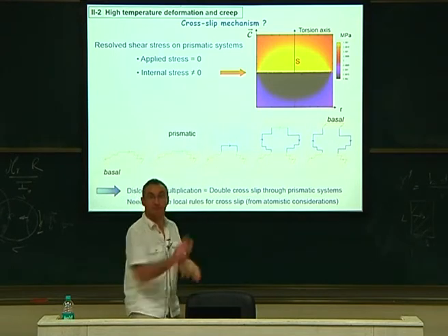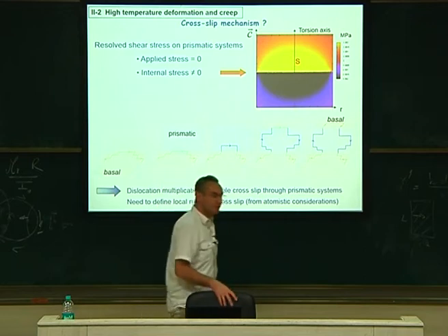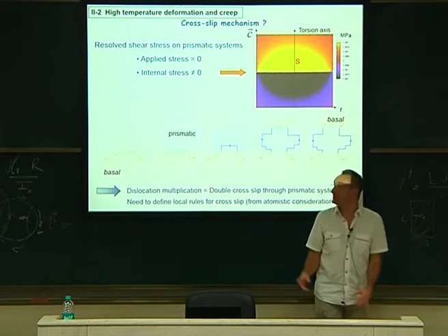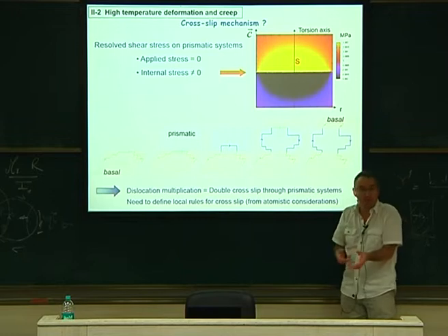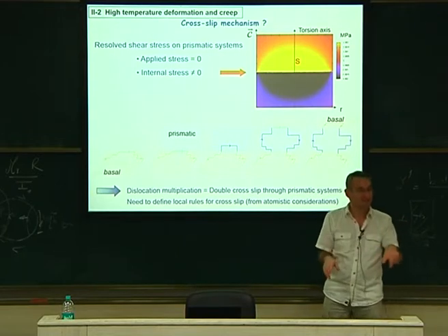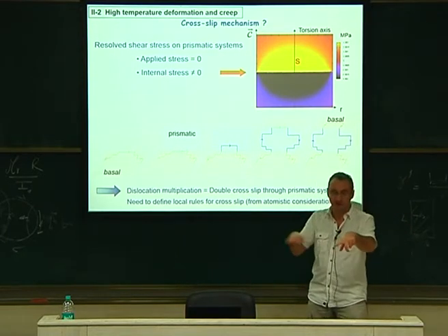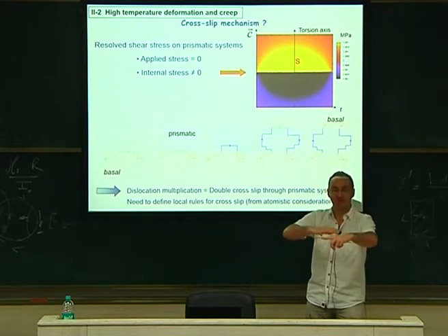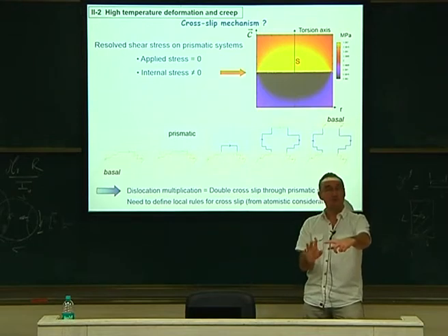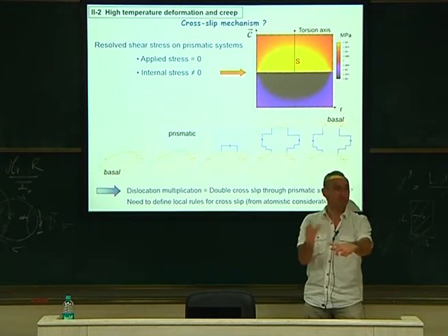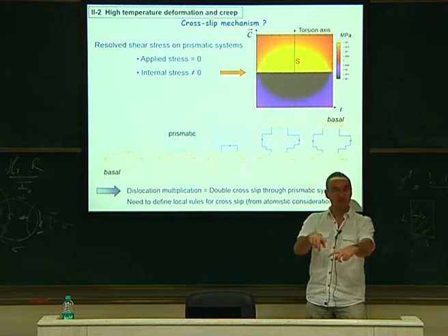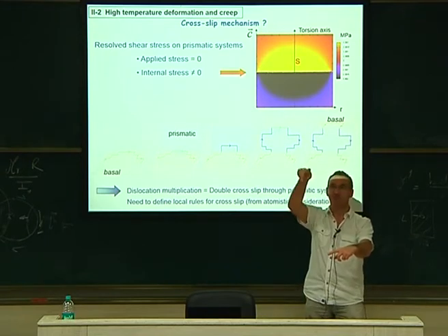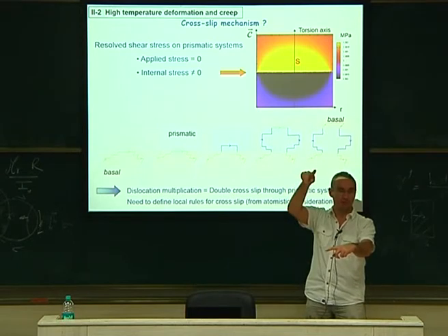So it's like something which is repelling very, very easily. My colleague from Grenoble said that it's actually like a pileup. In a dislocation pileup, you have exactly the same thing. When you have a pileup of dislocations, the dislocations are stuck in their plane, like this, but the stress to cross-slip, even in FCC, is very high locally at that place, and then decreases when you go far away from the pileup.